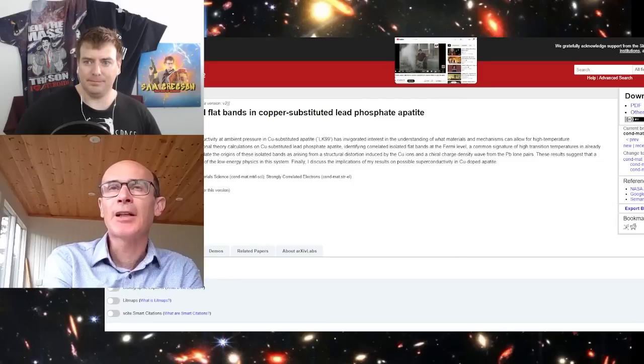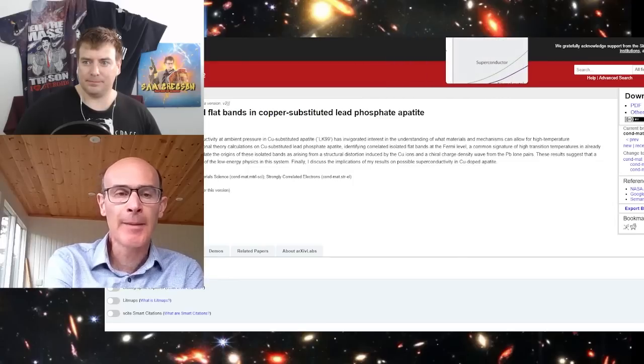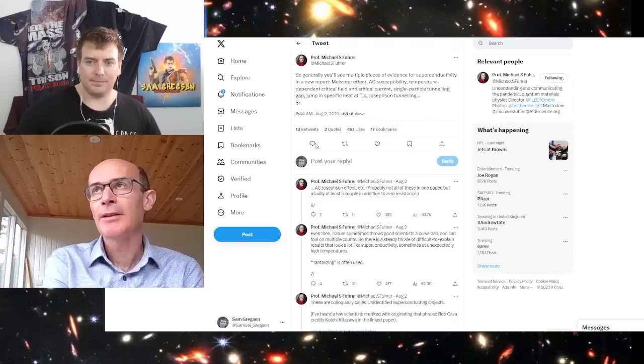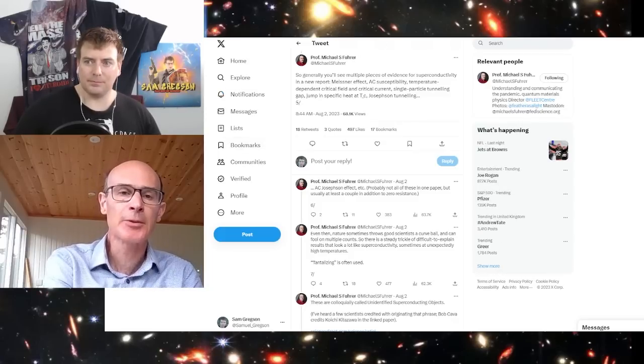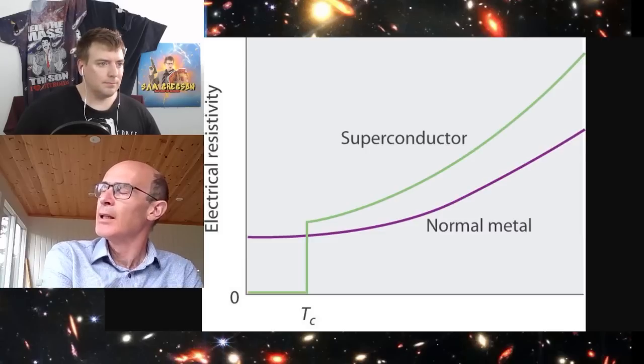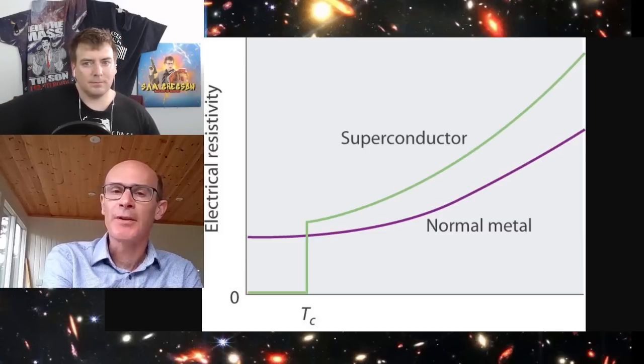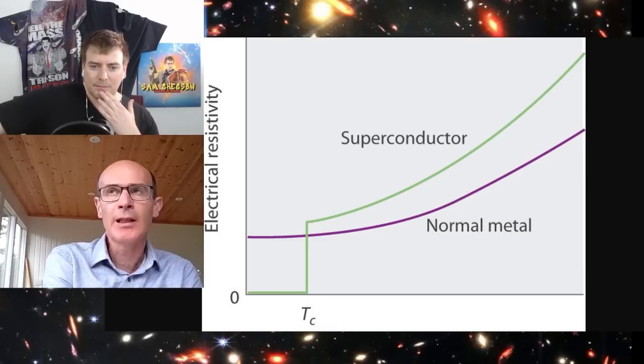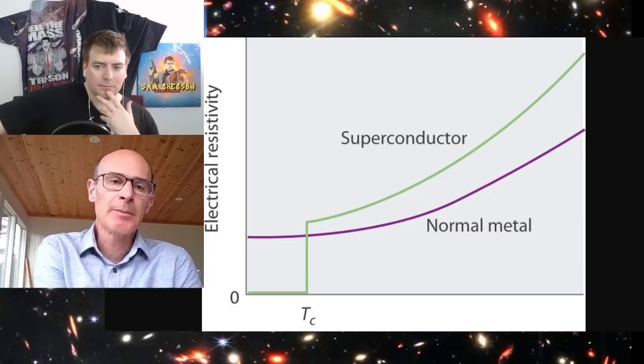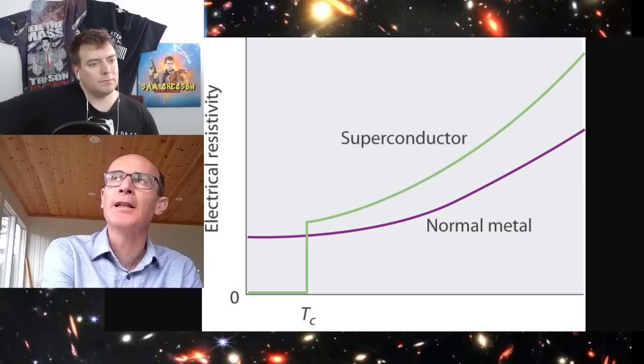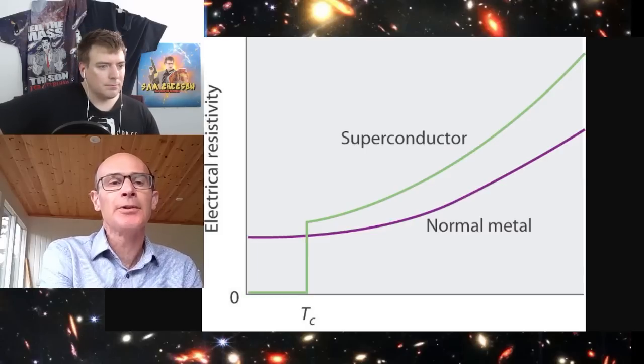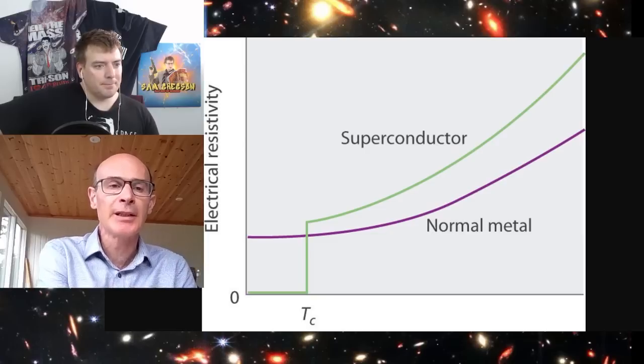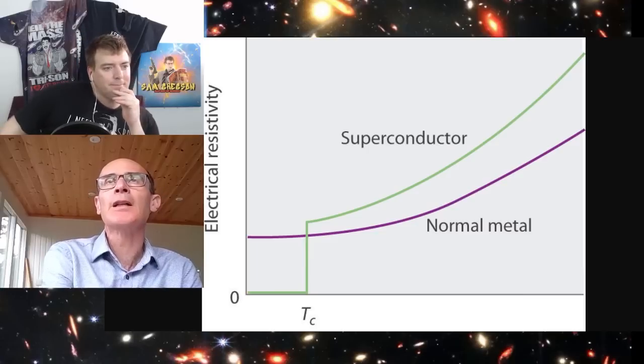Yeah, the main test I would do would be to measure the diamagnetism and show it passing through the phase transition, passing through the superconducting transition. In the original paper, there is a measurement of the magnetic susceptibility. Conventionally, to test a superconductor, you would cool the sample through the superconducting transition in the absence of a magnetic field, cool it into the superconducting state. You would turn on the magnetic field and measure how magnetic it was, and it should be a perfect diamagnet. So it perfectly repels the...